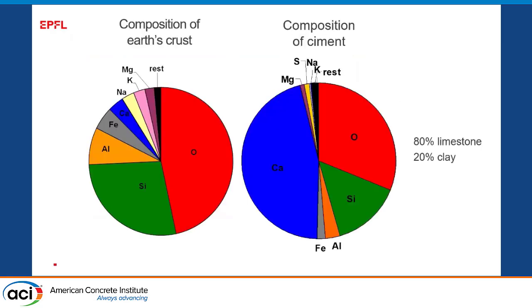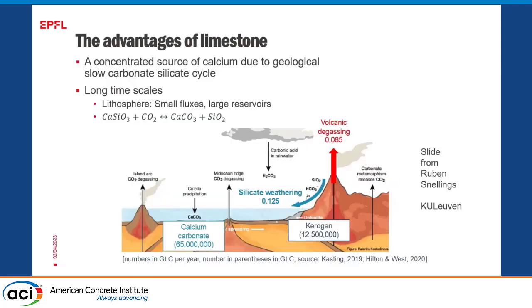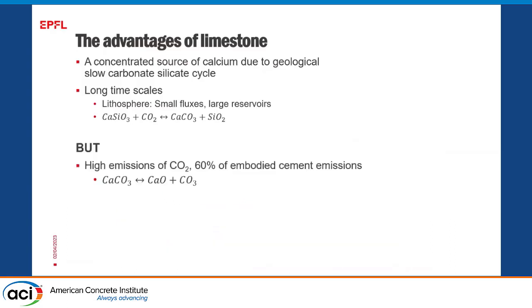So this basically means we're limited to Portland cement, and the big difference we see between the composition of the earth and the composition of Portland cement is this concentration of calcium. And we're very fortunate because nature's done a lot of the work for us of concentrating that calcium in the form of limestone. So this is what is called the slow carbonate-silicate cycle. You get weathering of these common rocks, and then they carbonate in the Earth's atmosphere, picking up CO2. The problem is this is quite a slow process because it does involve the fact that these rocks have all got to dissolve. So the advantages of limestone are a lot, but the problem is, of course, then you get back all the CO2 afterwards.